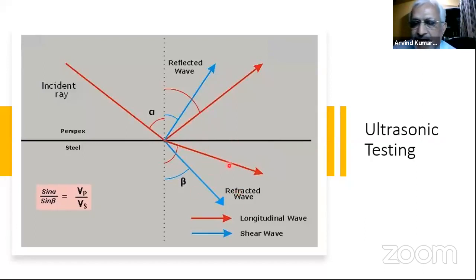That is, I can have 45 degrees, 60 degrees, or 70 degrees, with only shear wave. I have excluded the longitudinal wave from the material. And then I can vary this angle to get 60, 70 or 45. So that is how the angle beam probes are generated. And this is the law which is called Snell's law. The sine of alpha upon sine of beta is equal to the ratio of the velocity of the material in plastic and the velocity of the material in steel.